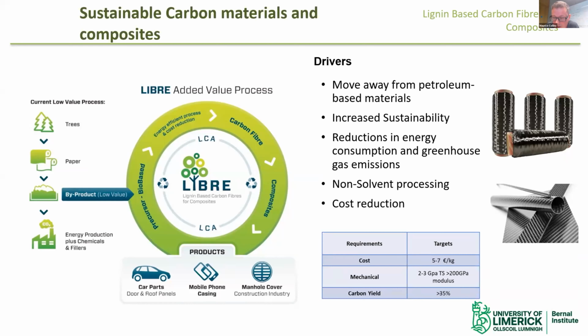So another driver was cost reduction. So we wanted to reduce the costs. So we were looking at costs of about 5 to 7 euros per kilo. Mechanical properties is always something that's extremely important when it comes to carbon fibers. And our targets were 2 to 3 gigapascals and 200 gigapascal modulus. Now you remember from the previous presentation by Steve that the high end for natural fibers is about 0.5 gigapascal tensile strength, and a modulus of about 40 gigapascal. So you can see that these targets are way higher than typical natural fiber mechanical properties. Carbon yield, we were looking at greater than 35%, and we actually achieved higher than 50%.